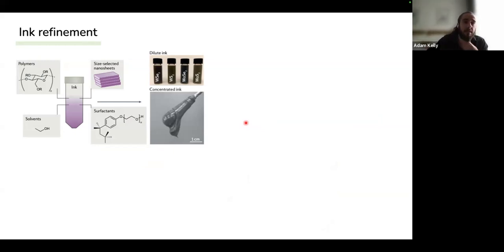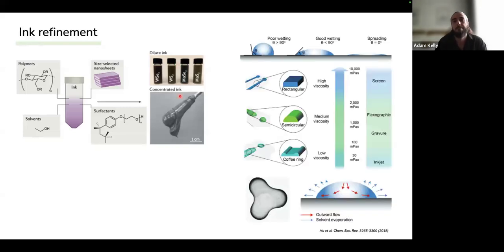Now, usually to make an ink, you will take your dispersion, which will contain polymers for stabilization, perhaps, or to control the viscosity. You'll have surfactant to affect things like surface energy. You will choose an appropriate solvent, usually one that can evaporate very quickly after it's been printed. And then you will take your active material, which you will have size selected previously. We also have a lot of tunability here. We have a dilute ink for processes like inkjet printing, and then concentrated inks for things like screen printing.